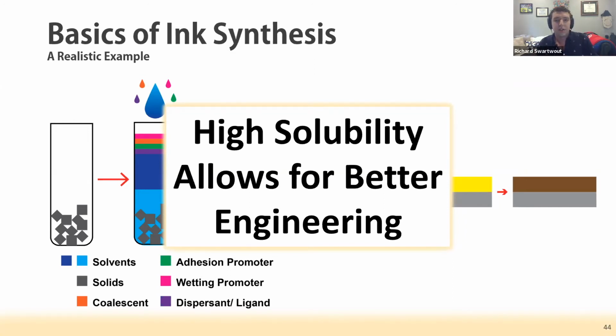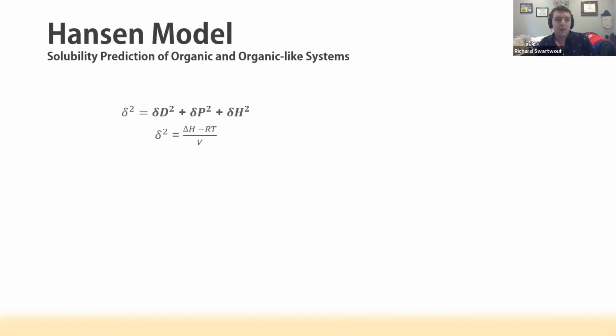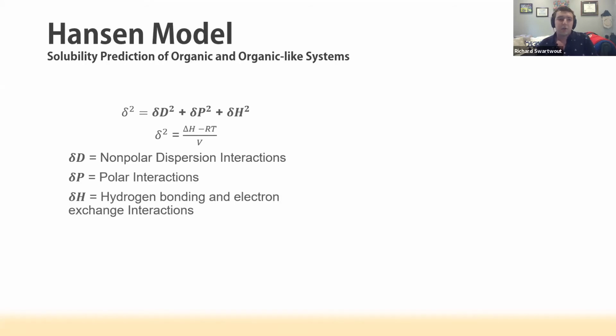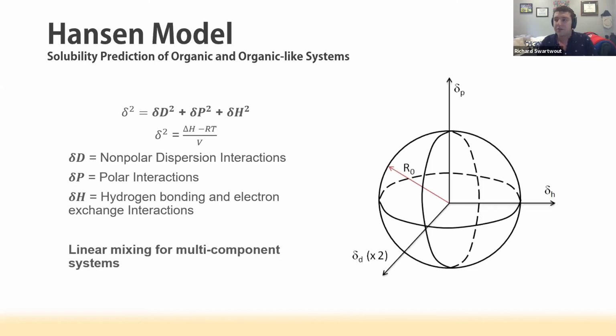The way the industry has done this traditionally is through the Hansen model. It's a 3-component model, all with partial solubility parameters: non-polar interactions, polar interactions, and hydrogen bonding. What's nice about the model is it assumes linearity. So if you take a multi-solvent system, all pure solvents will have fundamental D, P, and H values. You mix them together and linearly combine the D, P, and H to get an equivalent D, P, and H for your new system. For solids of interest, there's one more parameter, which is the interaction radius. All this defines is the range at which it's soluble within Hansen space.